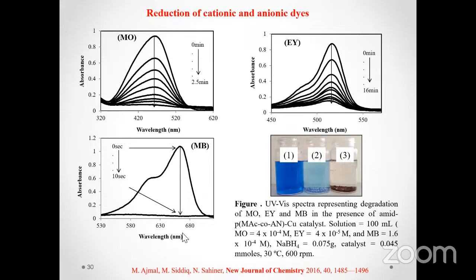In this case, there was another interesting observation when we used methylene blue as a pollutant. In case of methylene blue, we observed that the catalytic action was very, very fast as compared to that in methyl orange and eosin yellow. These methyl orange and eosin yellow are negatively charged dyes, while methylene blue is a positively charged dye.